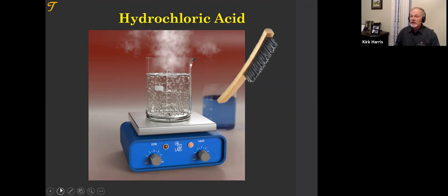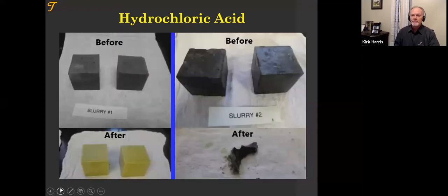Because if you put a cube in and just let it soak, you create an insoluble salt and you do not get much corrosion at all. So I can report no corrosion. In fact, once I start transporting and removing that insoluble salt, it can be quite corrosive.